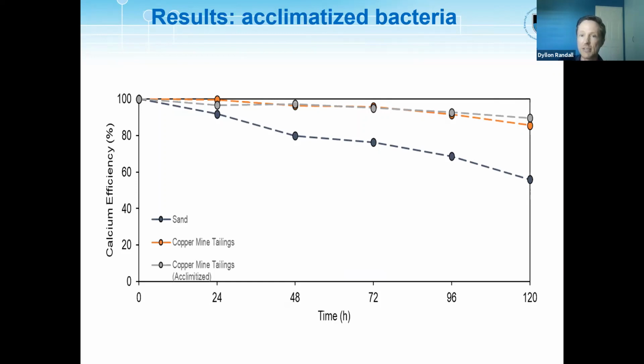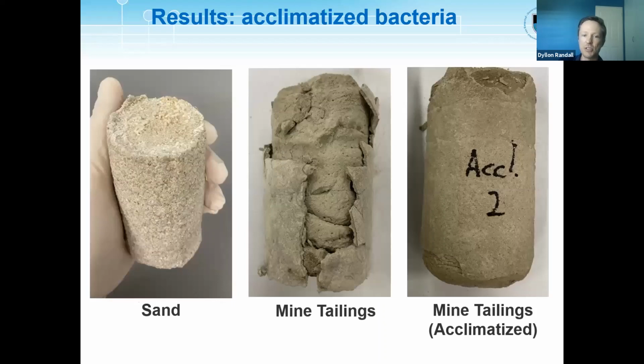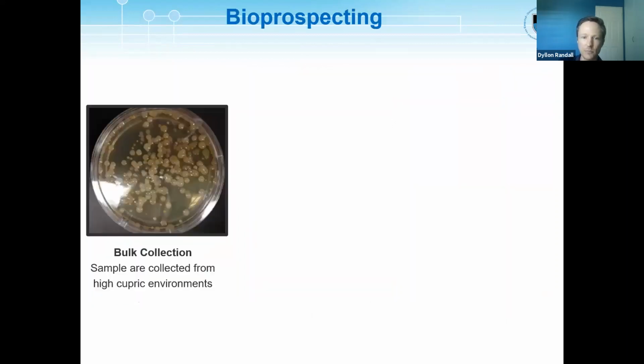So we tried to acclimatize the bacteria by incrementally growing them in higher copper concentrations. But even after successively acclimatizing them to 600 milligrams per liter, which was similar to what the copper tailings were, they still gave similar results. And so this is just a comparison of the three: the sand, the mine tailings using the normal bacteria, and then the acclimatized bacteria. We see that the shell isn't as fragile with the acclimatized bacteria, but it's certainly not as strong as the sand column.